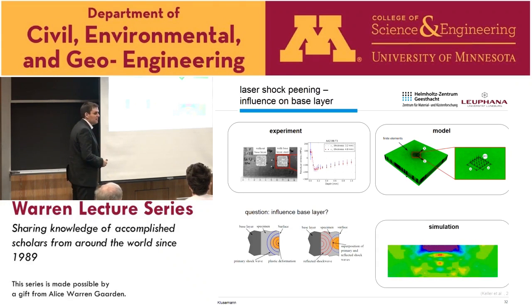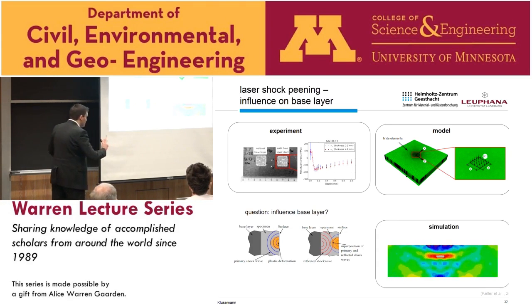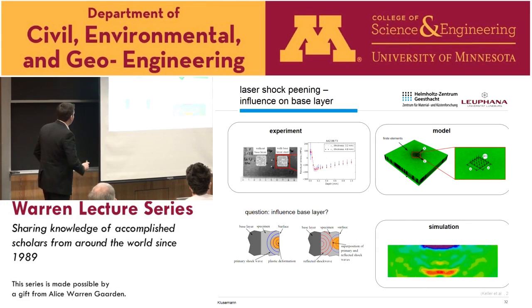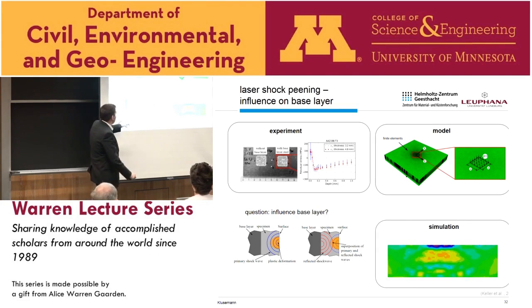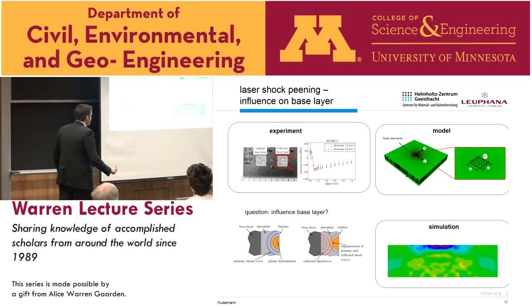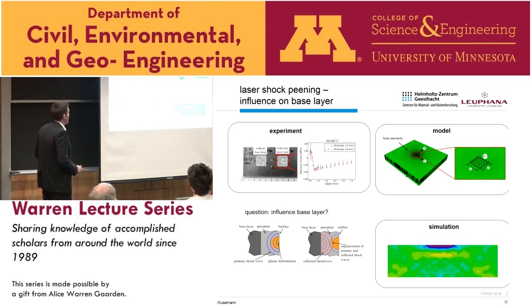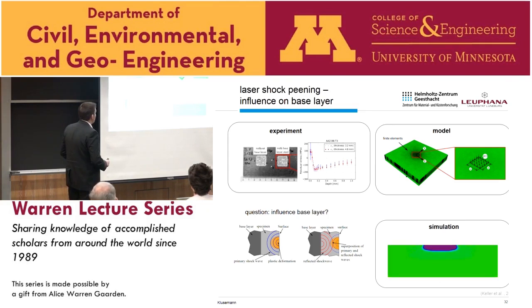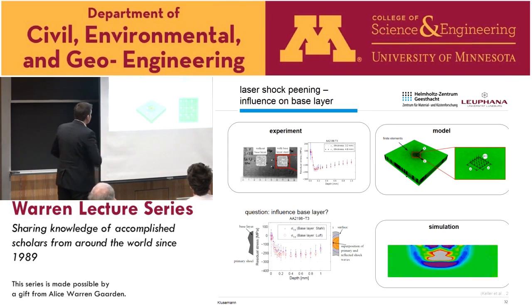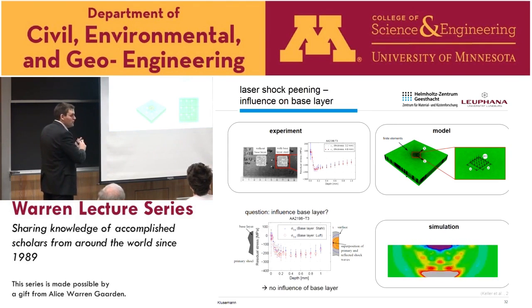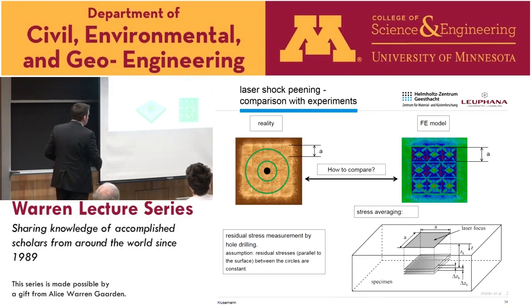We set up a finite element model for that, investigating then, of course, the influence of the base layer. And what we could show is, well, there was no influence. We could take it, so everything what we did experimentally was fine. Here also some experimental data. So if we take steel or air, it gives us the same response. So this was now a stage, no influence of base layer.